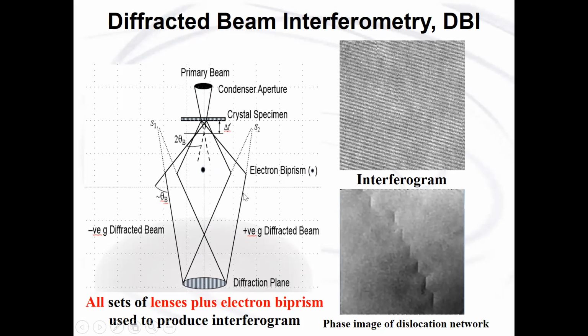We use the intermediate lenses to image the specimen, from the in-focus diffraction right through the Fresnel imaging mode and almost to the specimen in focus. We can't go as far as the specimen in focus, but the intermediate lens allows us to determine which observation plane we actually want to see. We also use the projector lenses to magnify our image so that the fringes produced by the interference of the two beams are easily seen by our camera.